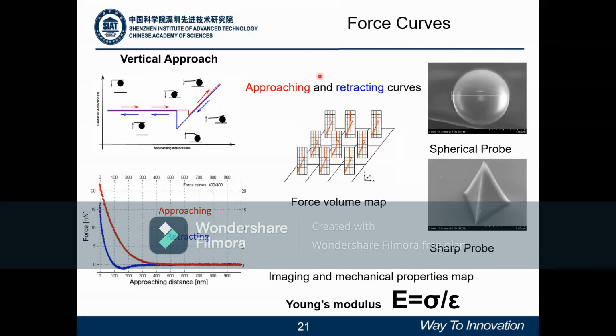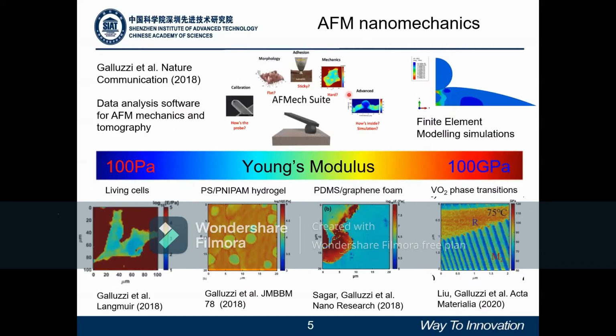So when this operation is done on a regular grid on a surface, it's possible to have a force volume map, and then a map of Young modulus that gives some intrinsic mechanical properties of the sample. In this case also, the proper shape of the probe should be selected depending on the sample. So here I want to give you some examples of AFM nanomechanics. After data analysis, it's possible to get information on Young modulus from very soft samples, with a range around 100 Pascal, up to 100 gigapascal.